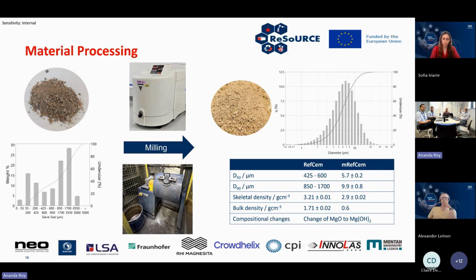So to achieve that, we did some milling. We did lab scale milling, looking at kind of 20 gram scale. And then we upscaled this to a multi-kilogram scale. And we managed to achieve D90 below 10 microns.